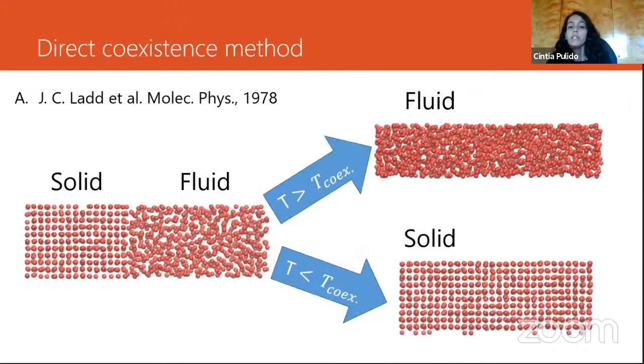We employ the direct coexistence method. This example is for a pure system. So we begin with a solid and a fluid. If we simulate this system above the temperature of coexistence, the system will become fully a fluid. It will melt. But if we are below the coexistence temperature, which is the melting temperature, all the system will solidify. So we do different simulations at different temperatures, and we are able to estimate this coexistence temperature.